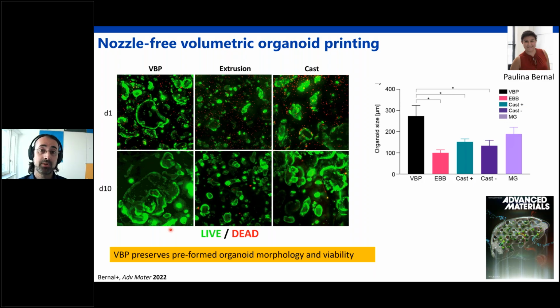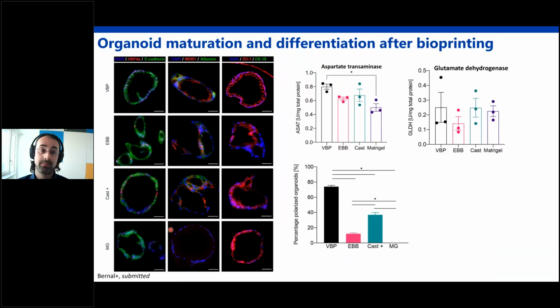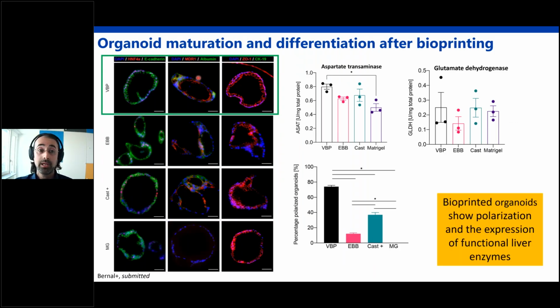It's not just a matter of size though, it's also a matter of function. So these organoids can mature faster because they start a bit further ahead in their differentiation process. And we see that only in the volumetrically printed group, we actually have polarization. So the organoids should present some markers, in this case MDR1, which is an ion pump that in the liver pumps compounds from the hepatocytes' body into the intrahepatic bile duct. They should express it only inside the organoid, and that's exactly what we see here, something that is instead missing in all the other technologies and also in the Matrigel control, but that's understandable because Matrigel is a matrix for organoid expansion and not for differentiation in reality. Of course, we also have an expression of certain liver enzymes, but indeed more important, we have this polarization.